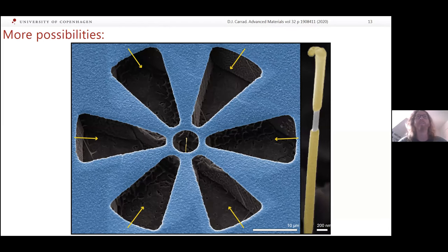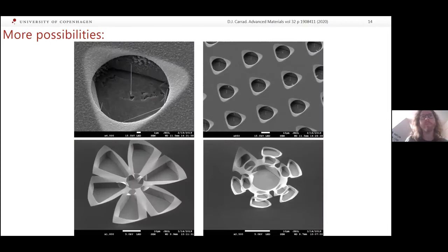for instance, by having these full shell nanowires, where now this nanowire is sitting in a spherically symmetrical configuration where you deposit six times around the nanowire to coincide with the six facets that the nanowire has. And then you form these patterned full shell wires. And this is kind of important for some talks, I think tomorrow, about the possibility to use the flux to generate Majorana modes and other interesting physics. And again, if you want to make different kinds of devices, you just change the number of bridges or their dimensions.